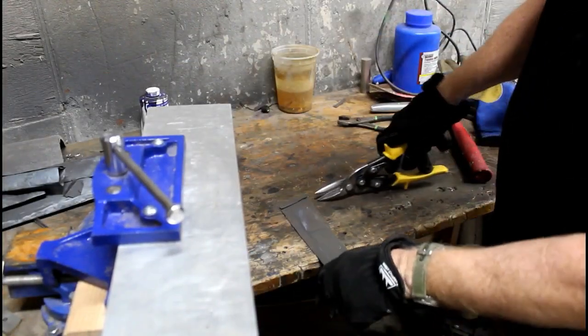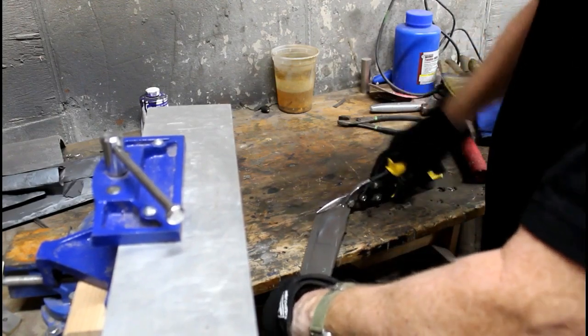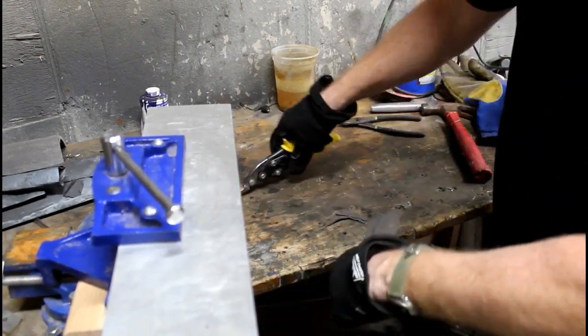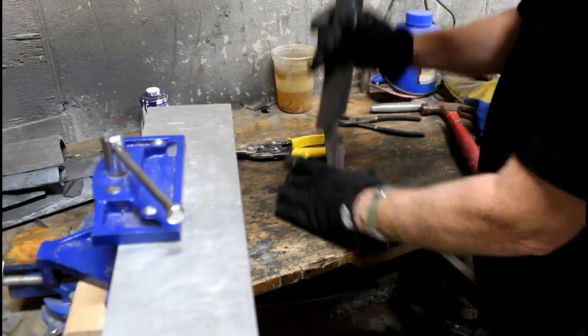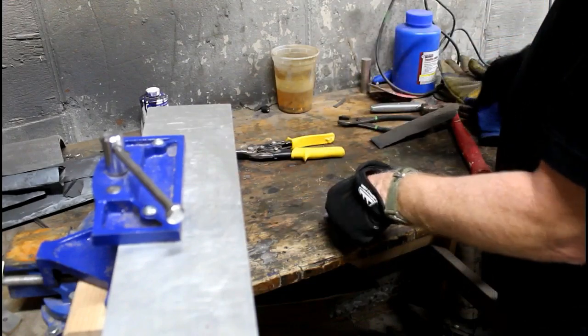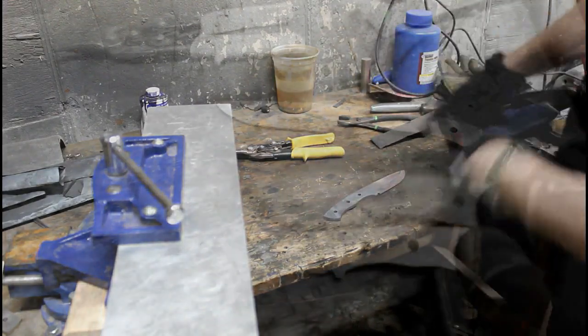And then after this, it goes in for sub-zero quench in dry ice, and then it goes into the oven for tempering, a couple tempering cycles. Now every type of stainless is different. AEB-L, we heat treat 1950 degrees for 15 minutes.